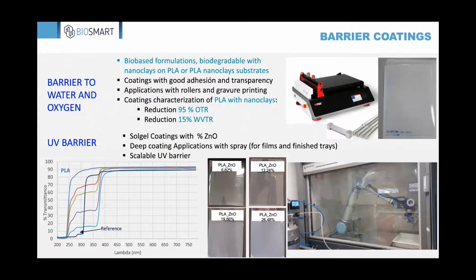Concerning the barriers to water and oxygen, also the nanoclays has been used in the PLA in the trays as a compounding, and also as a layer film in order to improve the barrier properties. And it has been possible to reduce 95% the oxygen transmission rate, and reduce 15% the water transmission rate. Concerning ultraviolet barrier, it has been achieved using zinc oxide nanoparticles, applying sol-gel coatings, and it's possible also to apply by spray.